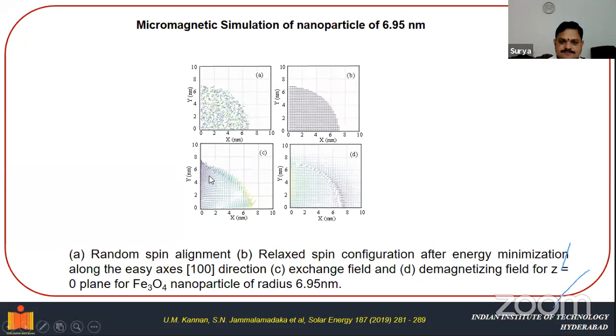What you could see is that the exchange interaction, or the exchange field, is restricted to the boundary of the nanoparticle, whereas the demagnetization fields extend out of the boundary of the nanoparticle. So this demagnetization field actually helped in enhancing the efficiency of our solar cell device.